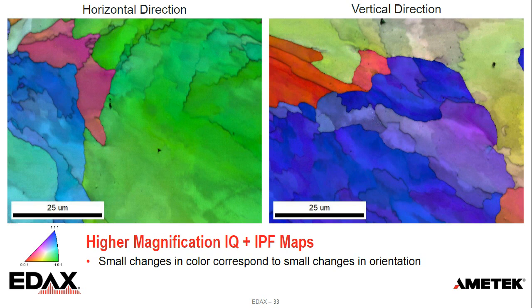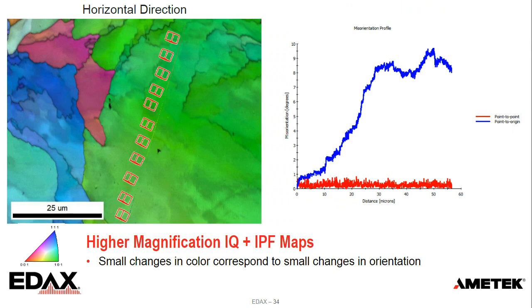And so if I look at this in terms of a misorientation profile, you can see on the left, I've drawn a line from the bottom to the top within that single grain. I've overlaid on there unit cells along that profile line. You can see that along the line there are small changes in orientation.